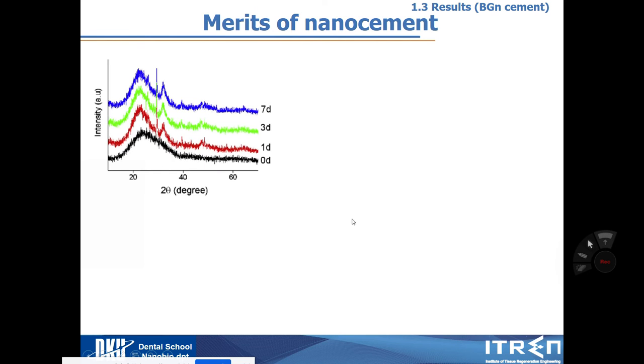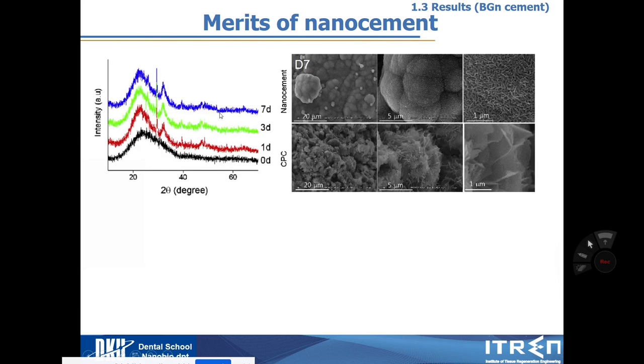And then I check their bioactivity. So this is the peak of HA, which means that this nanocement after setting has bioactivity. So when I look at their surface, they show this kind of hydroxyapatite, typical morphology. And then when you look at this CPC, this is the commercially available bone cement.